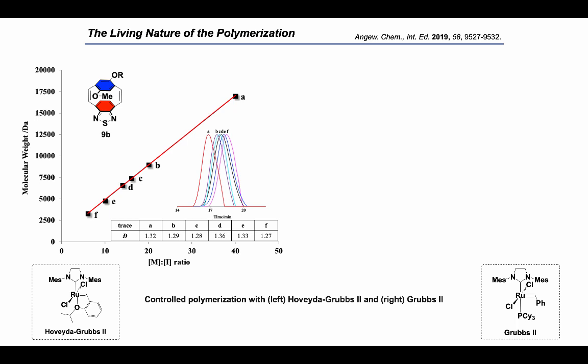Performing full polymerizations with varied monomer to initiator ratios, using Hoveyda-Grubbs 2, shown here, we observed a strong correlation with the observed molecular weight, which was exciting for us to have this hypothesis partially confirmed. Additionally, at each data point, the molecular weight distributions were all below 1.5, so they remained low as with the previous trials, which is generally a threshold for a polymerization being deemed controlled.